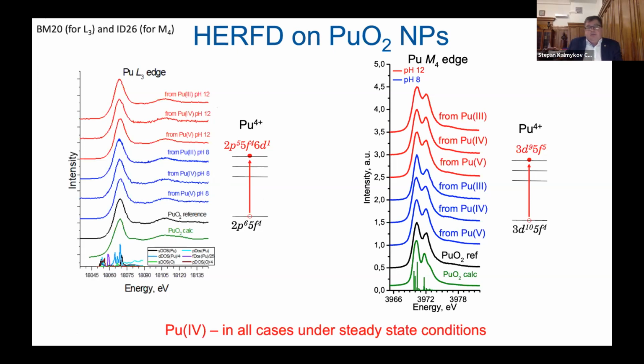The reason is that even if we have an admixture of some other oxidation state, the L3 edge is not that sensitive towards redox admixtures, because 5f4 electrons are not involved in the L3 edge, compared with the M4 edge, where we have a 3d10 5f4 to 3d9 5f5 transition. So 5f electrons are involved, which means we are extremely sensitive towards the redox speciation, and we can define a very small amount of one redox state in the presence of the other redox state.